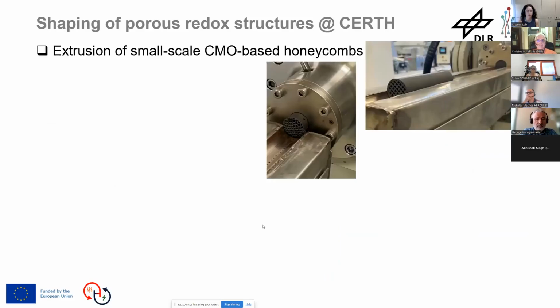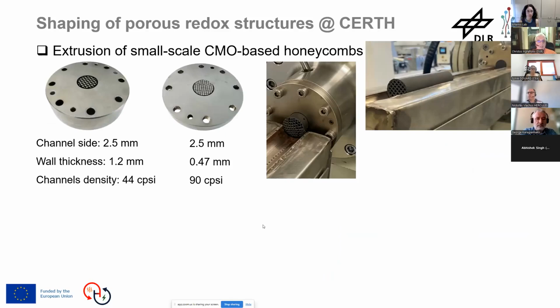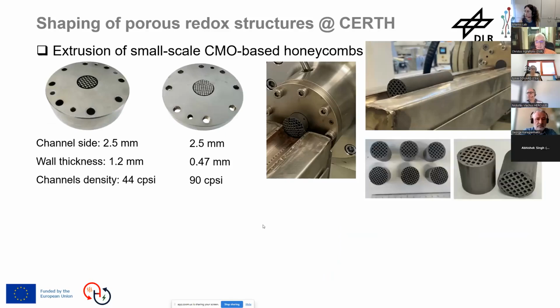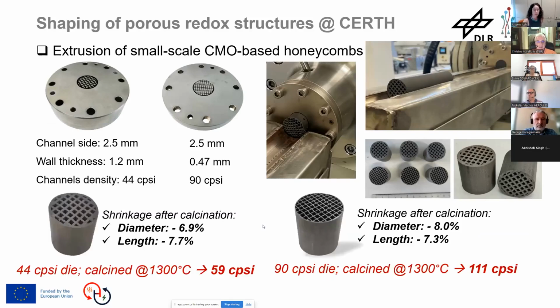And here, our colleagues at CERTH have started to make this kind of porous structures based on this perovskite composition. You will see some typical ones here, which are of the order of 1 inch diameter. You see how these are made with these extrusion dies, several variations with the cells. CPSI stands for cells per square inch, how dense or less dense the structure is. And here, for instance, we can see the finalized product that can be tested, and my colleagues at CERTH will present the testing results in the next presentation.